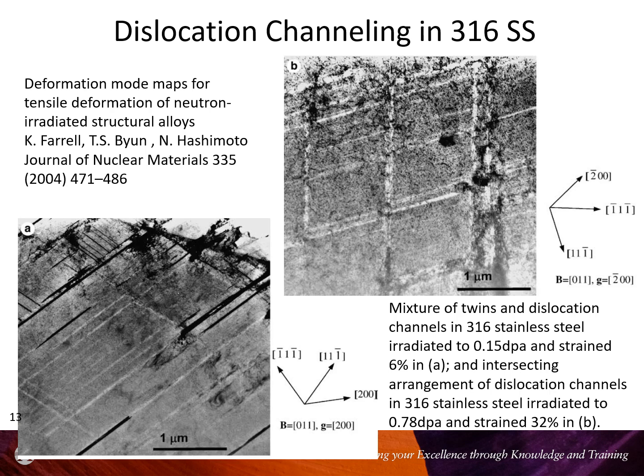So in getting to this amplification situation at a lock, there's been a lot of study about channeling, because I kind of think, in the mistaken belief, that channeling is an indication of this amplification happening. Well, as I explained earlier, channeling itself is a bulk shear. In effect, it becomes more like a twin when it advances, and the dislocations are not all lined up one behind the other like a train, and so the channel itself, when it interacts with a barrier, cannot generate the kind of stresses that Cottrell and Eshelby conceived of, and also Stroh conceived of,